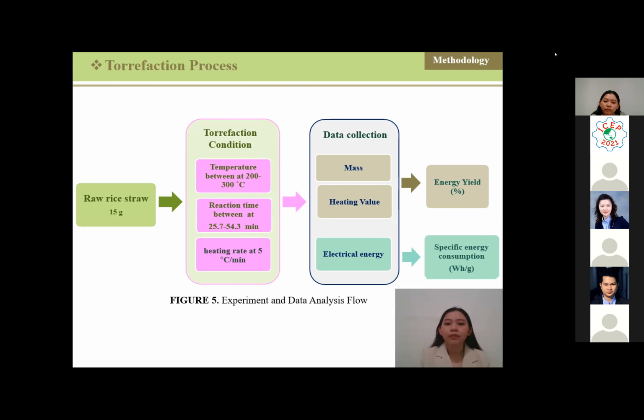The experiments were planned by central composite design between 200 to 300 degrees Celsius. Reaction time 25.7 to 54.3 minutes. The heating rate was set at 5 degrees Celsius per minute. Data collection includes mass, high heating value, and electrical energy for calculation of energy yield and specific energy consumption.